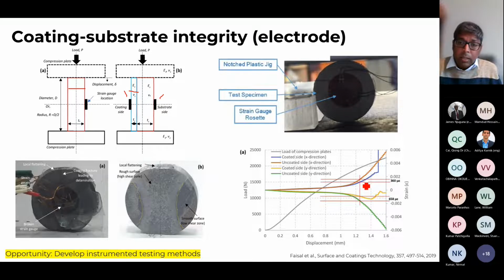Then we did a neutron diffraction measurement on this coating and compared the strain at which point the coating will come off or start failing. So we were able to see those features, and we were able to relate. This is a destructive test, so I was able to relate it with a non-destructive neutron method, because all these component electrodes, when you manufacture them, will go through various loading scenarios, twisting, bending, high temperature, thermal mismatch, all these things happen. So we need to understand how strong they are.